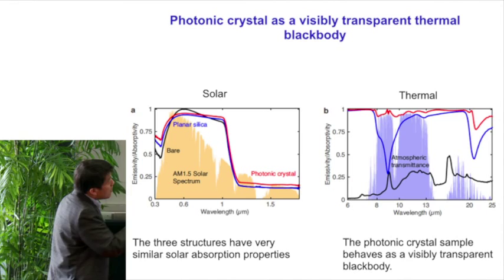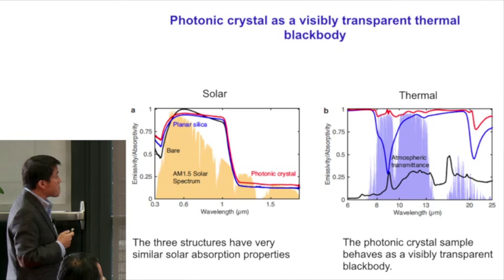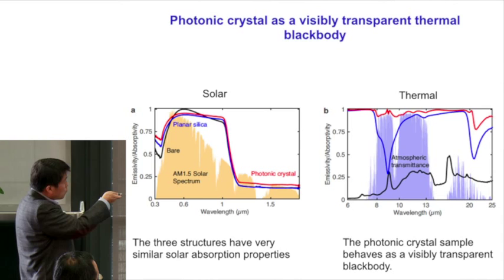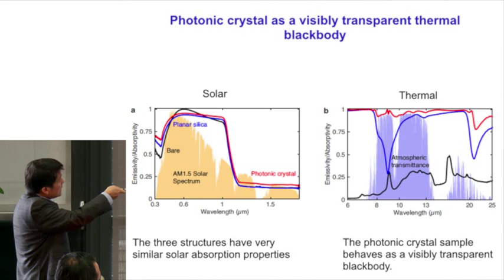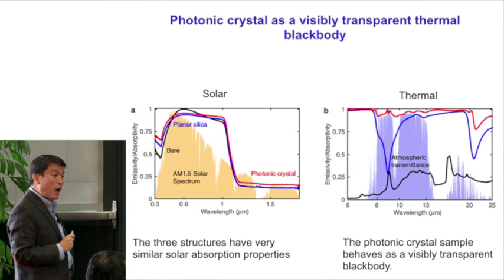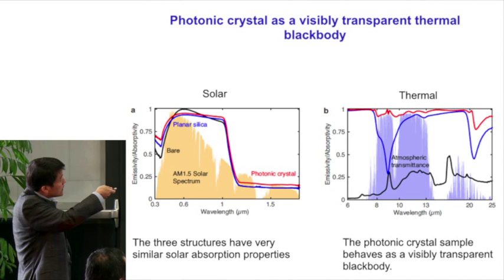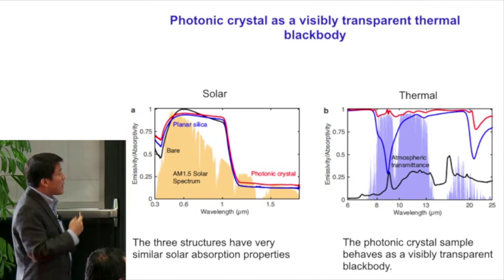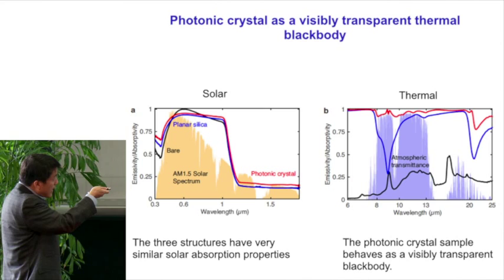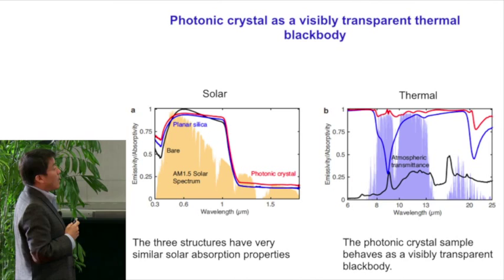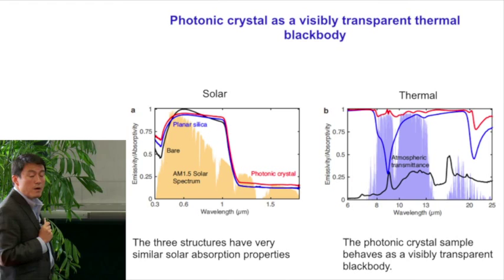On the thermal side, on the long wavelength side, on the other hand, the properties of the three structures are very different. The black curve here is the bare silicon sample, as I mentioned. It has relatively weak thermal emission. The blue curve here is the thick, uniform silica layer, about 500 microns thick on top of silicon. Silica has a strong phonon-polariton response. Consequently, the thermal radiation goes up quite a bit compared with the bare silicon region. But because of the index mismatch between silica and air, there is actually a pronounced dip inside the transparency window of the atmosphere, and therefore a thick silica layer is actually not optimum for radiative cooling purposes.